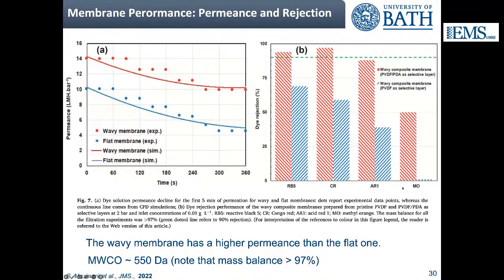We tried 4 different dyes, and what you see here is dye rejection. The columns in red are for the wavy composite membrane with the nanofiltration layer. And in blue, you have the wavy composite membrane with PVDF alone. So this is ultrafiltration, whereas the PVDF polydopamine is nanofiltration. And in fact, you see that the wavy membrane with the nanofiltration PVDF polydopamine selective layer has more than 90% rejection with Reactive Black 5 and Congo Red, and just shy of 90% with acid red. So the molecular weight cutoff is around 550 Daltons.